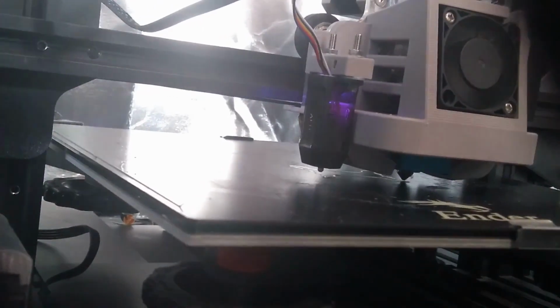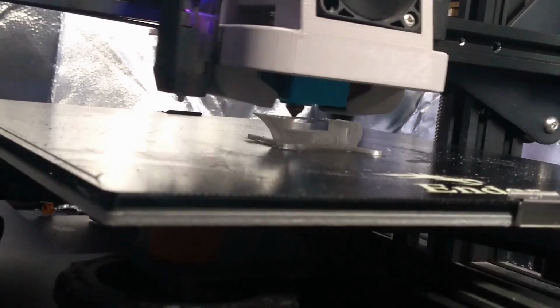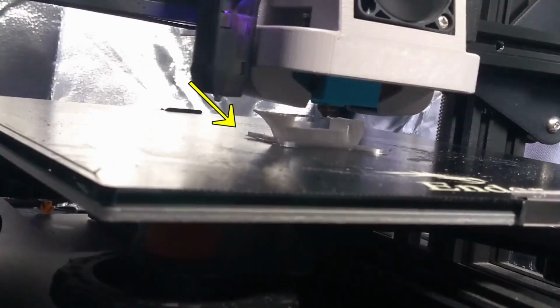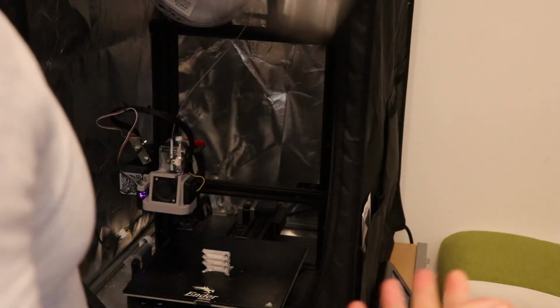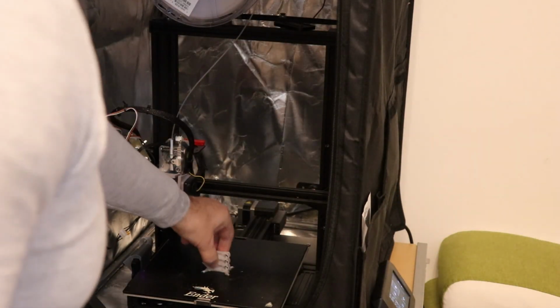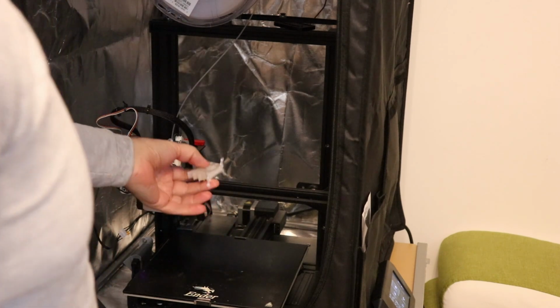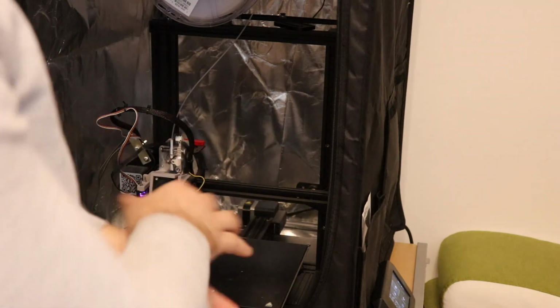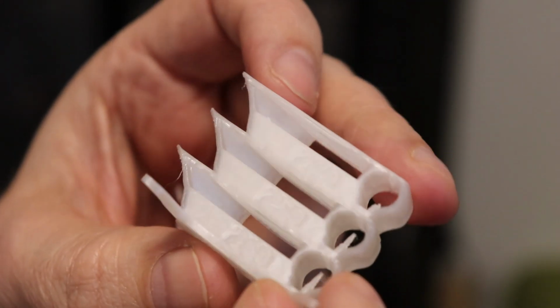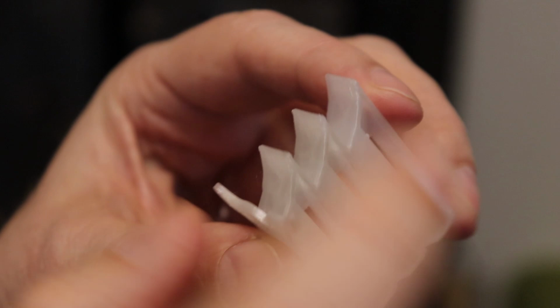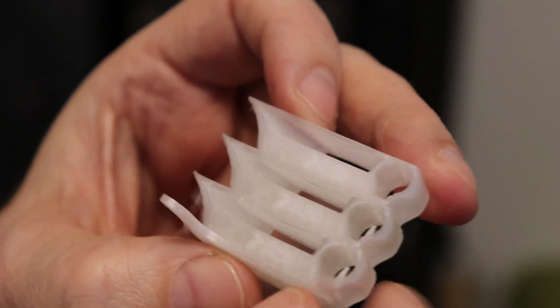The first layer goes down perfectly, and at the end of the first element I can see the only problem with some warping on one of the corners. It had really nice progress, so I left it there and it was quite easy to remove when it cooled down. Let's take a closer look. And here it is. It looks really good, much better than the ABS. The overhang is perfect, the bridging too.